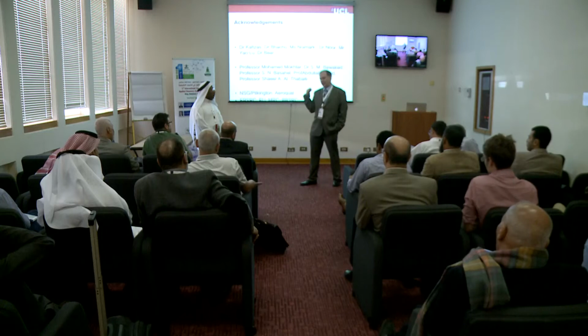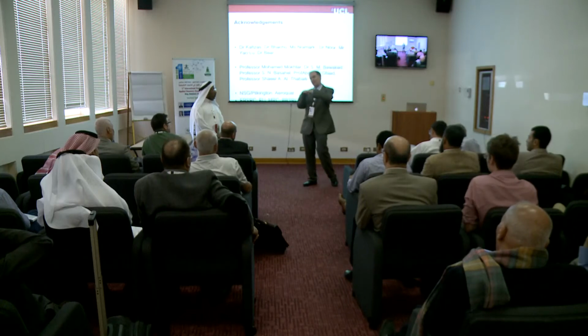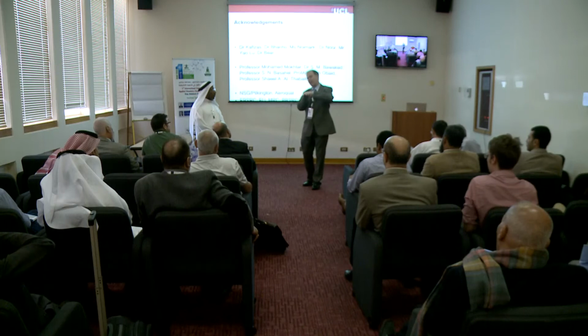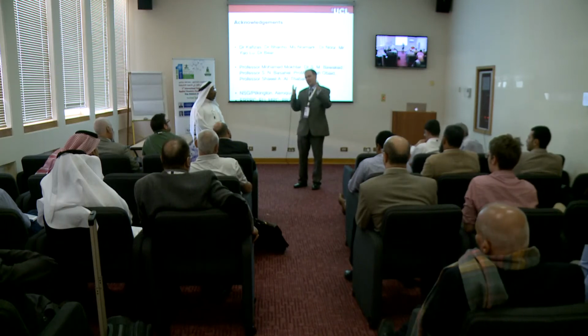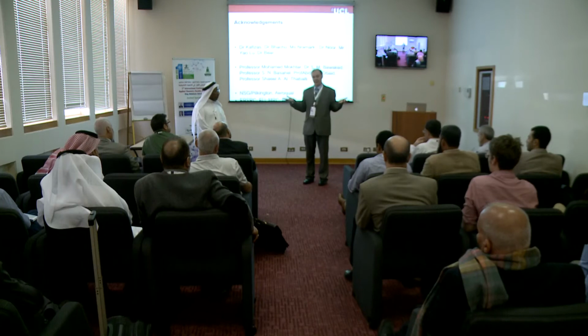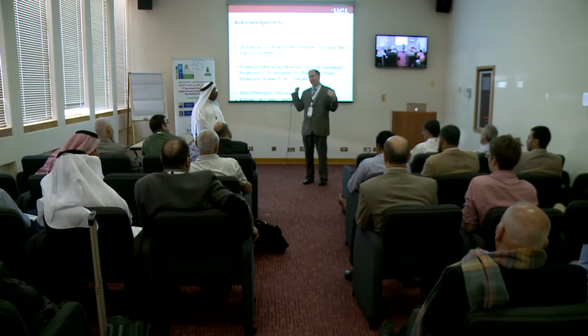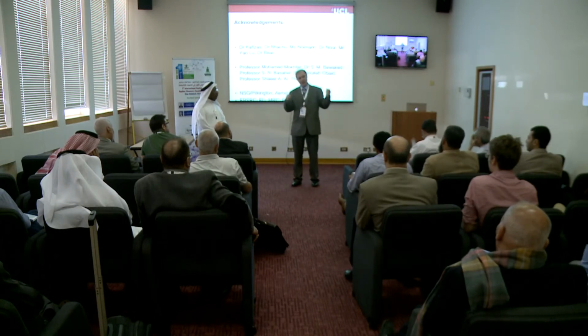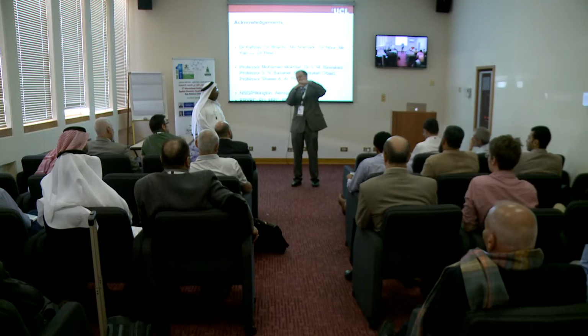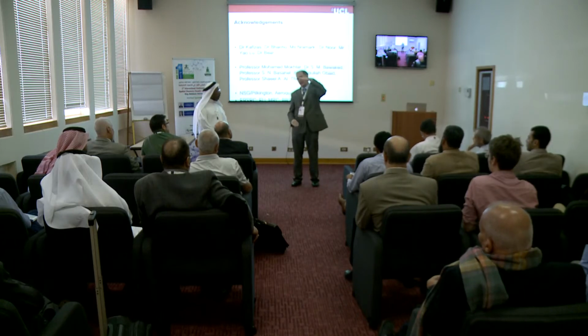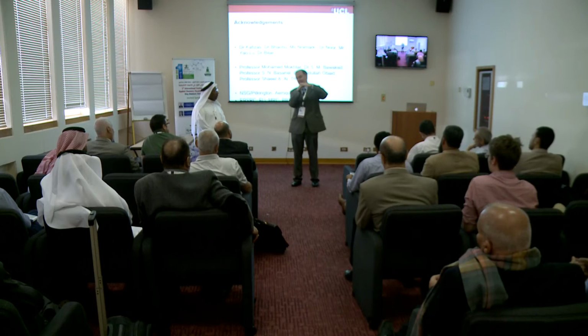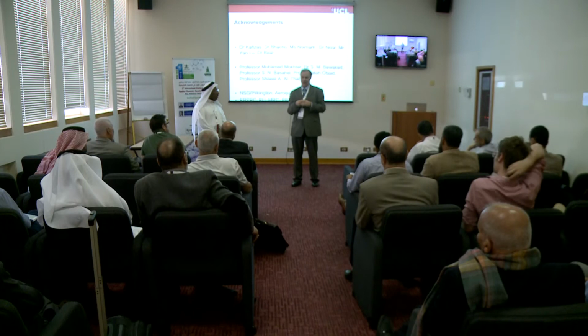One thing we're using them for is oil-water separation. We make membranes which love oil but repel water. If you have an oil-water mixture, or even just for straight chemistry, I'm the head of the department at UCL, and our undergraduates now use these as filters. All of you as chemists would have at one stage done a separation from an aqueous layer to an organic layer, or vice versa, and you always struggle at the interface. But we have a filter that will let all the organic part go through and keep all the water. Even if it's coloured, you can't see it, and it works really efficiently. That's using the superhydrophobic coatings.